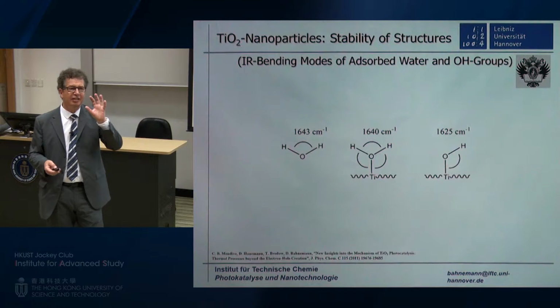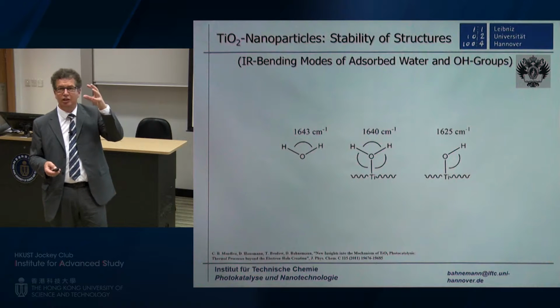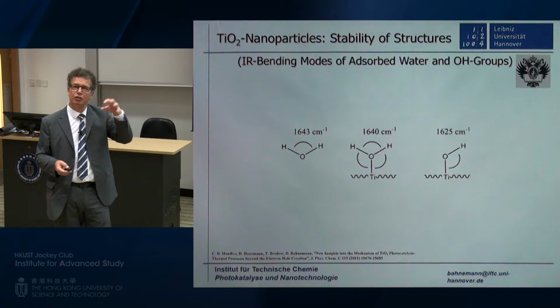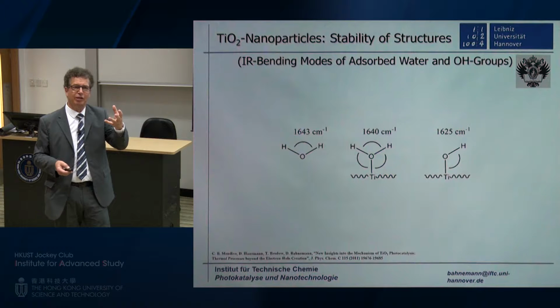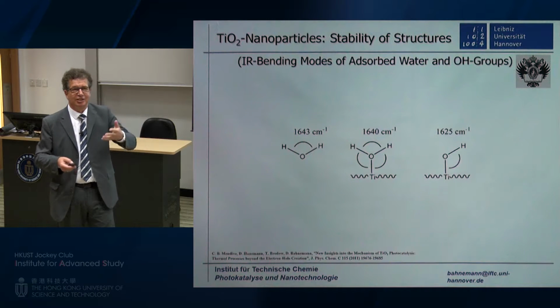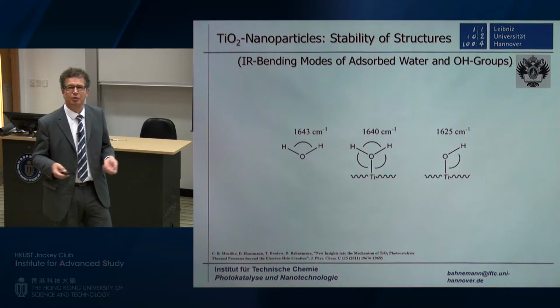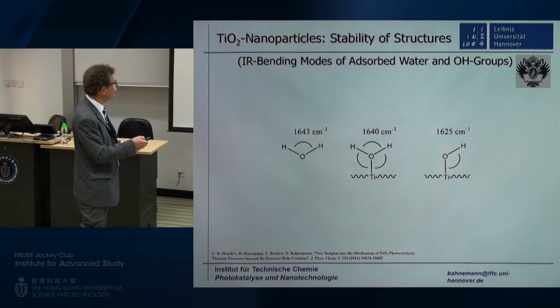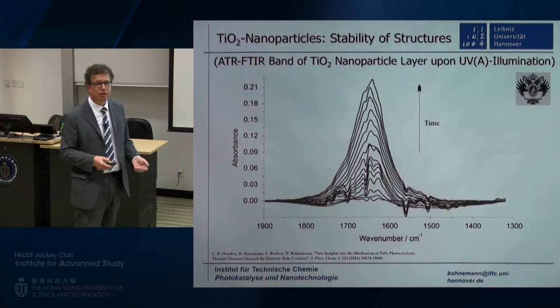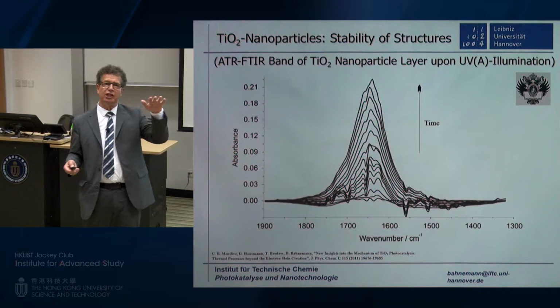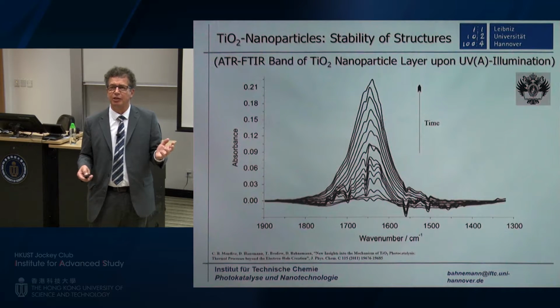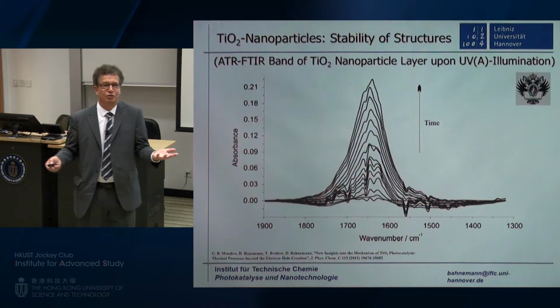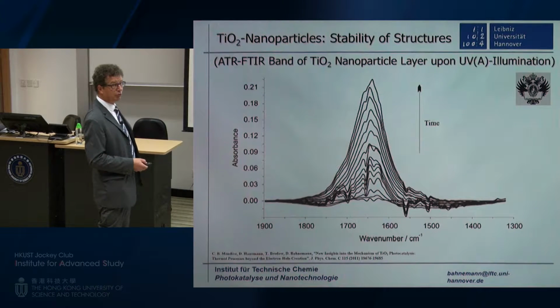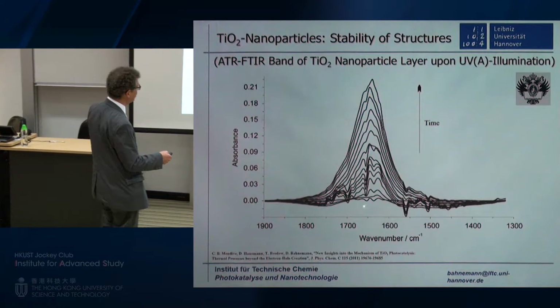Without adding any molecule, and I showed you before, you need a molecule, an adsorbed molecule, to bring about a chemical reaction, because otherwise, if you have no molecule adsorbed, there will be no electron transfer happening. So now we did the illumination of just the TiO2 water interface, and we expected to see nothing, because it's a blank experiment. But we see something, and the something is pretty strong.